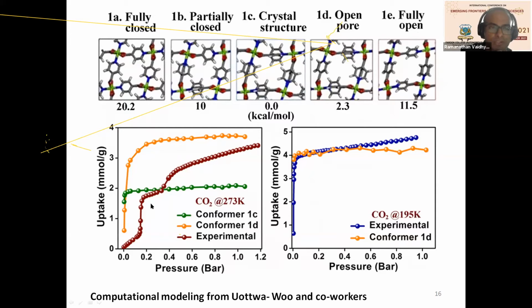So in this case, what he has done is he has calculated several configurations of the MOF by rotating the pyridyl units, and then identifying the energy associated with several different configurations. And then from the whole range of studies, he has identified only 5 configurations that have thermodynamically acceptable energies, of which one has the lowest relative energy. The others have slightly higher energies than that configuration. Okay. And this is actually the configuration from the single crystal structure.